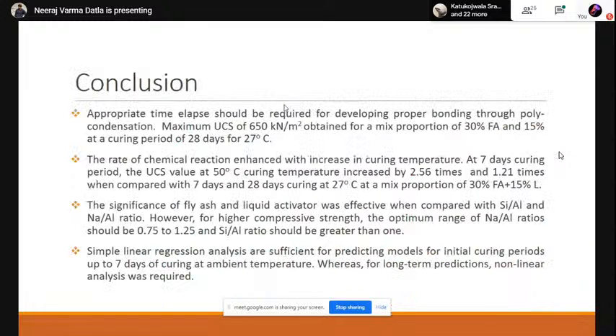And from these, these are the conclusions we have drawn. The strength always increases with increase in temperature and time. At 7 days curing, the UCS value at 50 degrees is very high, it is 2.56 times higher. And comparing the 7 days and 28 days compressive strength at 27 degrees and at 50 degrees, the strength is almost 1.21 times higher.